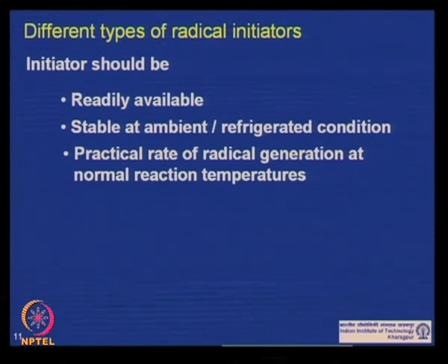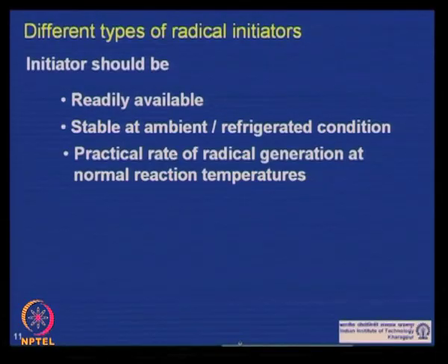So, there are three criteria an initiator should fulfill. One is that it should be readily available, especially for commercial application. Second, it should be stable at ambient condition. If you are storing it at room temperature, or even in a refrigerator, it should be stable, and it should not generate radicals under the condition of storage.